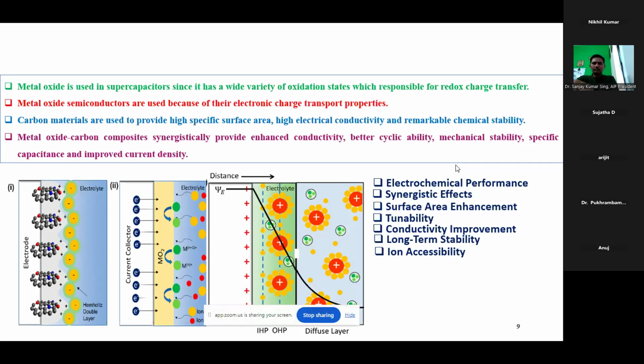Whenever I'm facing the limitations of metal oxide, and whenever I'm trying to overcome the drawbacks of carbon quantum dots, the synergetic effect gives better cycling, better stability, and desirable specific capacitance, which is responsible for higher energy density. And this is the mechanism according to this.